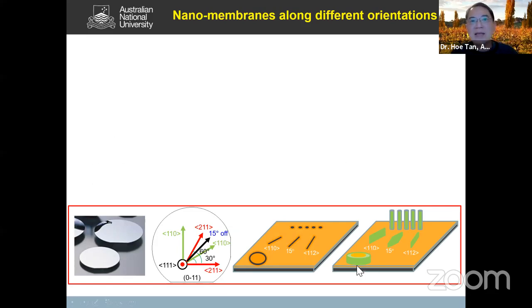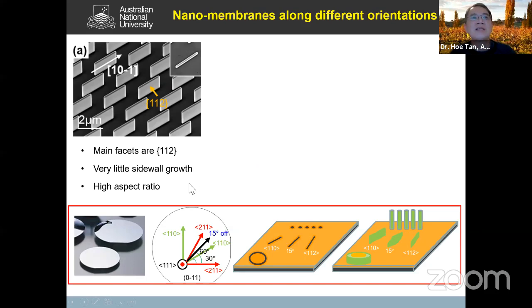So now I start off with my wafer. Over here, I've shown you before, we open up holes to grow the nanowire. But what happens now if I draw a line, along a certain crystallographic orientation? What will happen? Shown here is an example. This is an indium phosphide nanomembrane. Now, if I align my openings along the 1-1-0 direction,